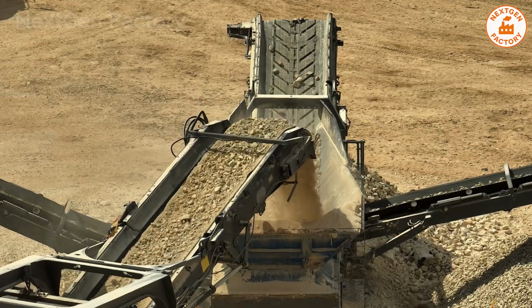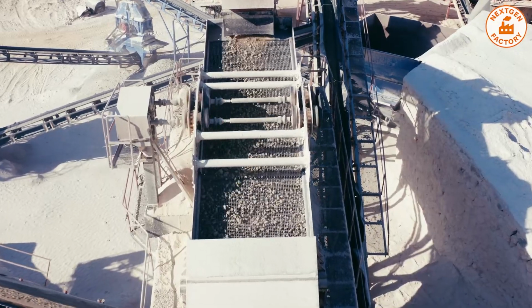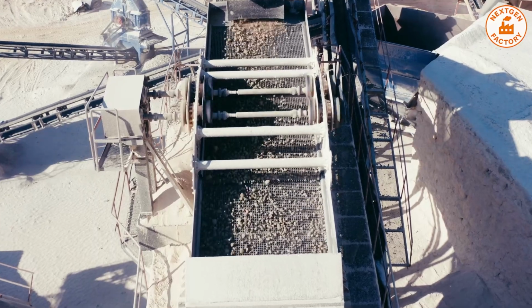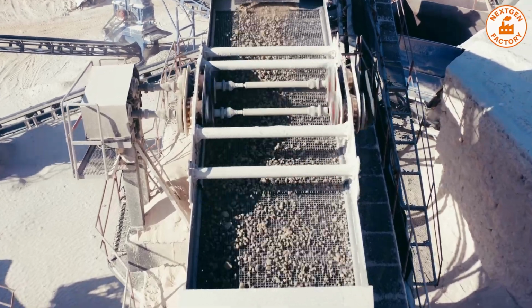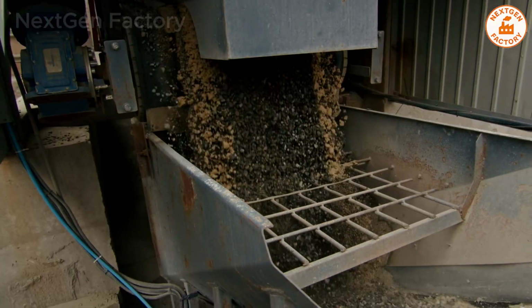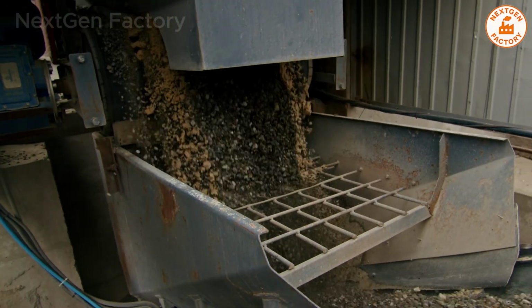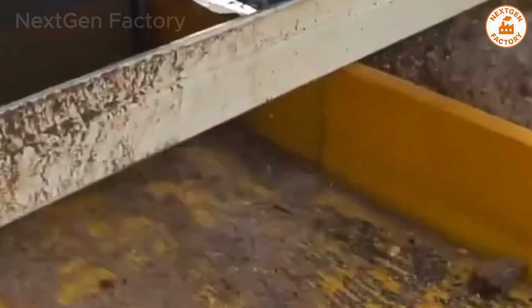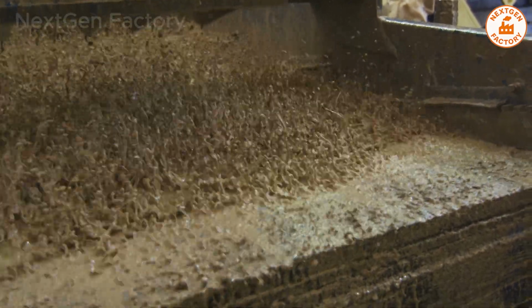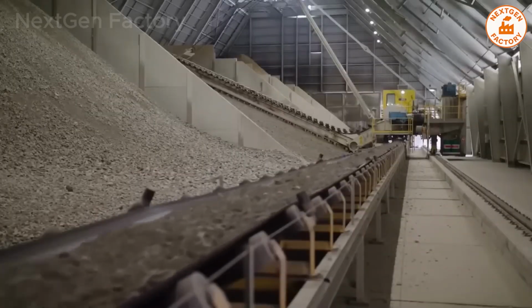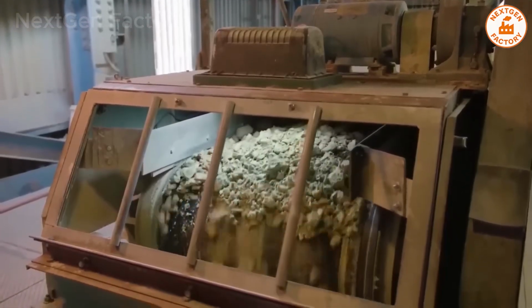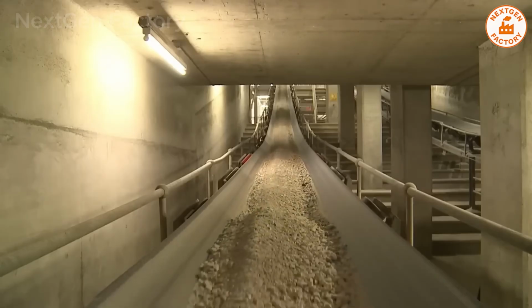The freshly crushed sand enters a sophisticated purification line. It begins with screening. Vibrating sieves eliminate oversized particles. A typical industrial screen might use a 30-mesh grid, 30 holes per inch, to ensure uniform grain size. Next comes high-pressure washing. Jets of water blast the sand, removing microscopic dust and clay. The mixture flows into agitation tanks where the grains are suspended and constantly stirred, allowing lighter contaminants to separate.